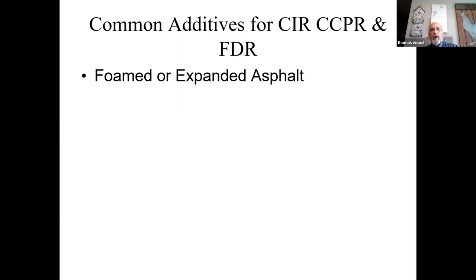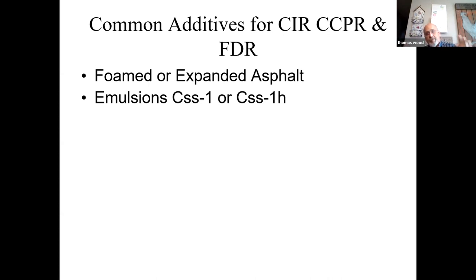So first we have foamed or expanded asphalt, for any Canadians that are listening. Then we have emulsions, and it can be a CSS-1 or CSS-1H if it's not engineered. In this climate, I would not recommend using a 1H, because CSS-1 is a softer base asphalt than CSS-1H. CSS-1H, if I remember right, the penetration range is 40 to 90 pen. So if we were PG grading that, which I know we don't PG grade emulsions yet, it would probably grade a minus 22, or maybe a minus 16, which would be prone to cracking.